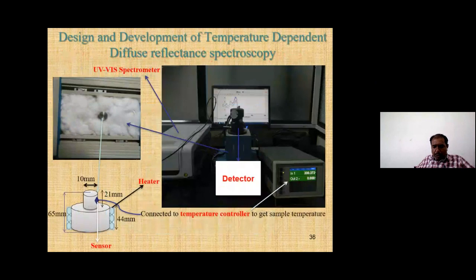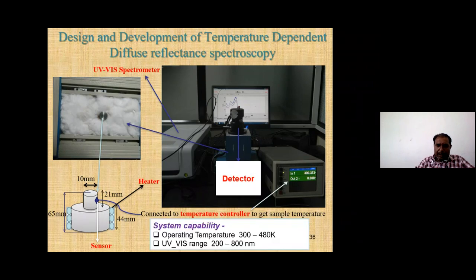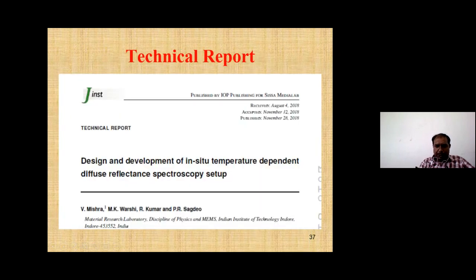In fact, one of my research students developed such a setup in the lab for measuring the temperature dependent optical reflectivity spectra. And this was a very simple setup. This particular setup can operate in a temperature range from room temperature up to very close to 500 K. Now we can go up to 550 K. And you can perform UV-visible spectroscopy with this setup in the range of 200 nanometer to 800 nanometer. This is something which we have published in one of the instrumentation journals.